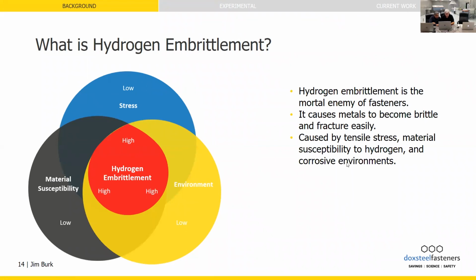It's an ASTM E140. You'll have correlations between Rockwell C, Brinell, and Vickers hardness in there. So yield strength, which is what people refer to more as a grade, the 125 grade being the minimum yield strength, there is a rough correlation between yield strength and UTS. In the higher strength materials, the correlation is about 1.1 or 1.15 times the yield equals the ultimate.